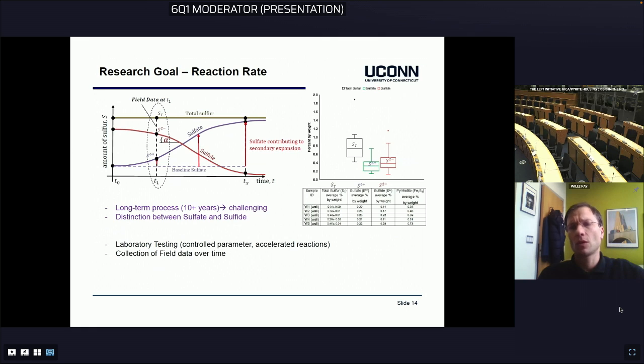So currently there's a lot of sampling going on. On the right side you see a table which is provided to the homeowners with what total sulfur, sulfate, and sulfides they have, and also the pyrrhotite. In general it's a long-term process, as has been said, 10+ years. It's challenging to quantify this, so we look for accelerated methods in the lab to develop the model. And as you see with the diagram, it's very important, given the time dependency, to distinguish between sulfates and sulfides currently present in the material. So we do laboratory control testing, accelerated reactions, and field data over time.